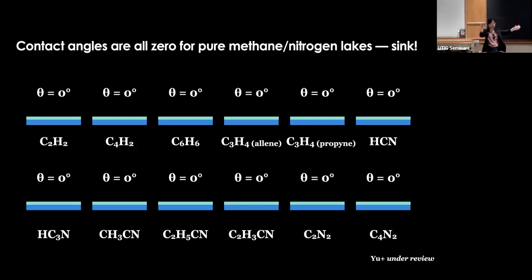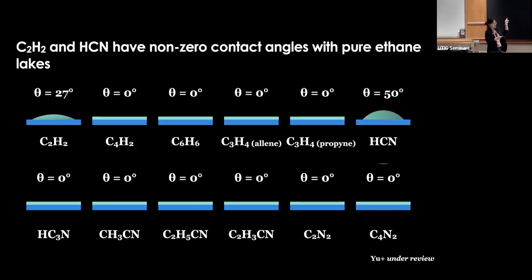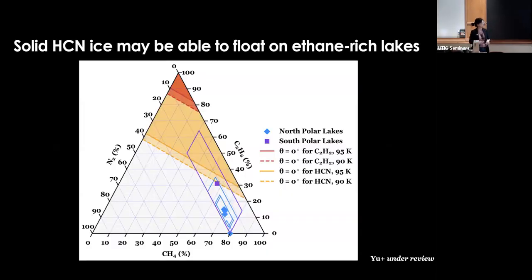They don't form a contact angle that's bigger than 0 degrees. All right. Well, for ethane, though, we do see 2 species that have non-zero contact angles finally. And because, again, the lake is a ternary mixture, I'm showing you a ternary diagram again. I'll try to do my best to explain this, but we have the ternary diagram.